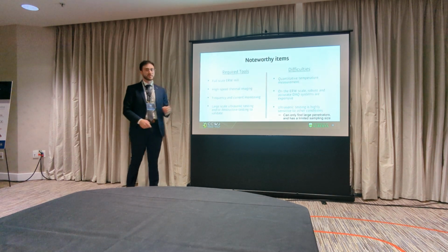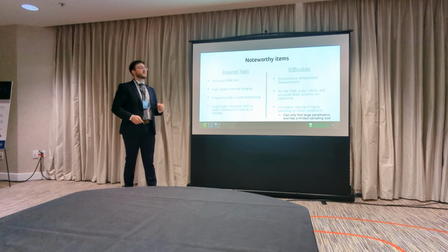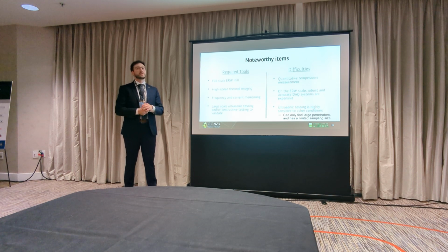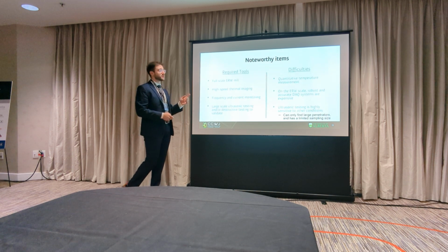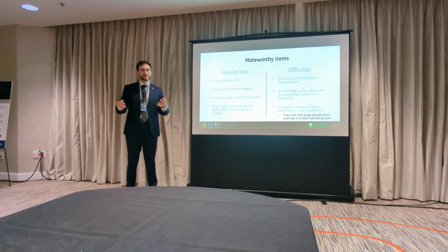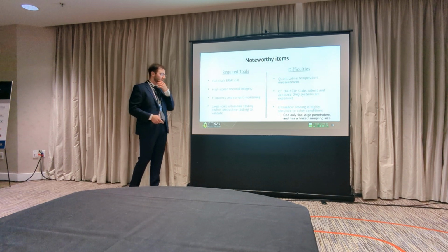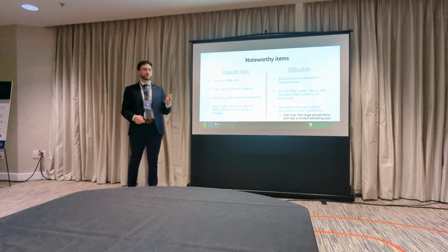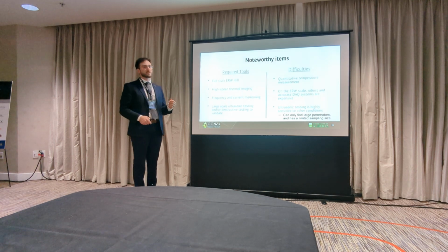Some notable difficulties with this project is quantitative temperature measurement. In ERW, you have multiple materials in the weld zone. You have your liquid film and then you have your solid gradient. And getting a temperature measurement of liquid steel is very difficult. On the ERW scale, robust and accurate data systems that sync with high-speed cameras are tough to come by unless you are the manufacturer yourself. And then ultrasonic testing is highly sensitive to other conditions such as your grain size, your temperature, and other conditions. So it can really only find large penetrators or large groupings of penetrators.